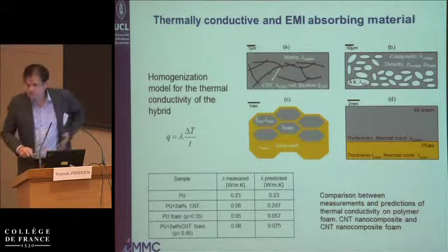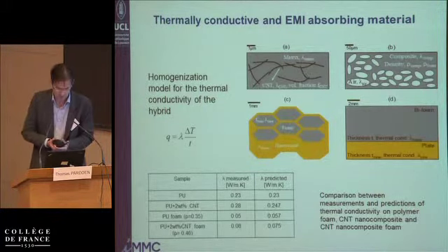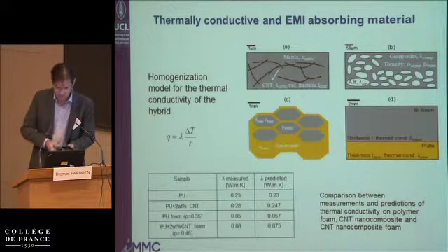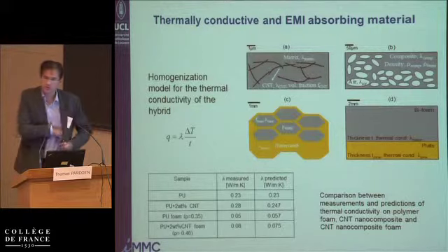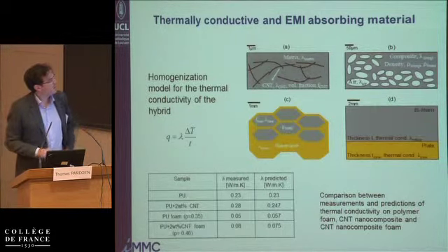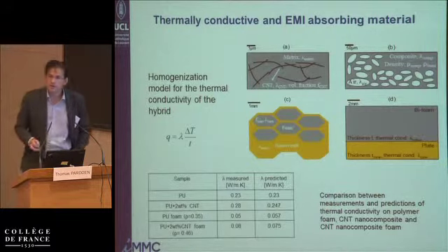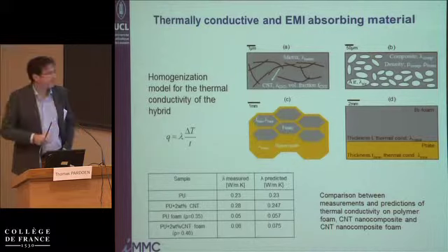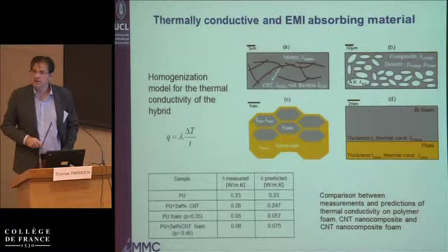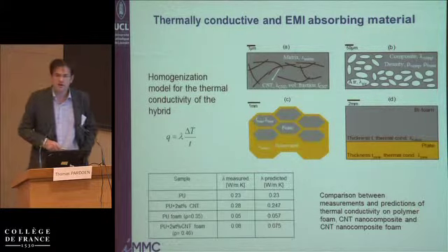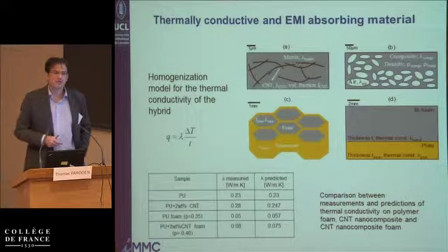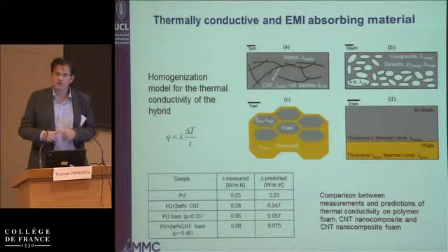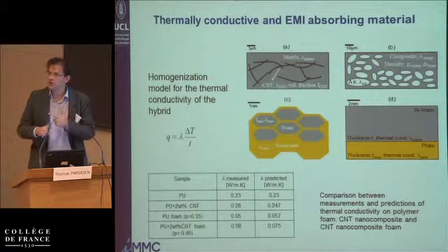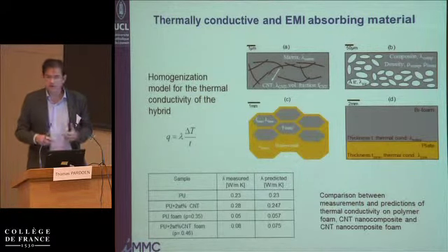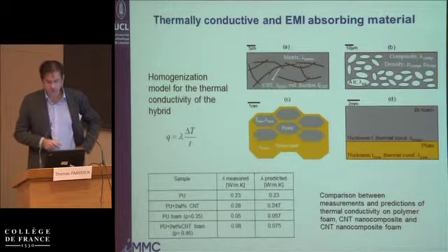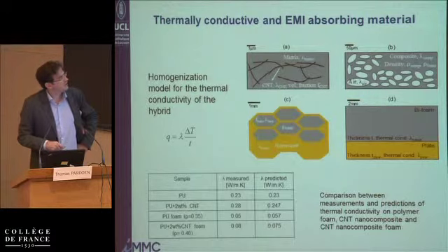So for applications in which you want to decrease the thickness of the sandwich, it's interesting. Now, in terms of conductivity, just a few words. We have played with many different polymers: polyurethane, polycaprolactone, polycarbonate, but of course we have here an insulating material. The additional conductivity coming from the carbon nanotubes is extremely small. Even though we have electrical percolation, the way heat is transported in the carbon nanotube networks is very poor. So basically, it's an insulating material.